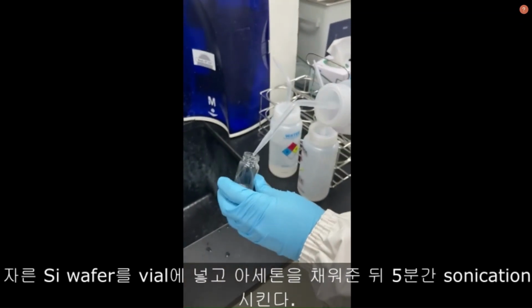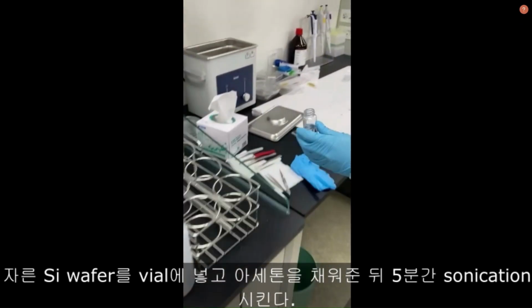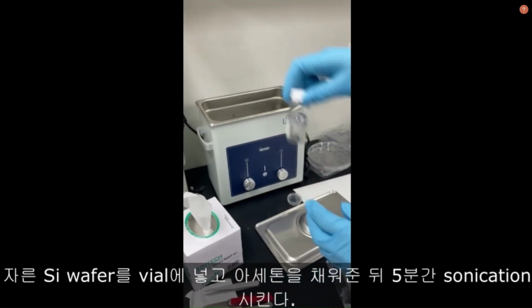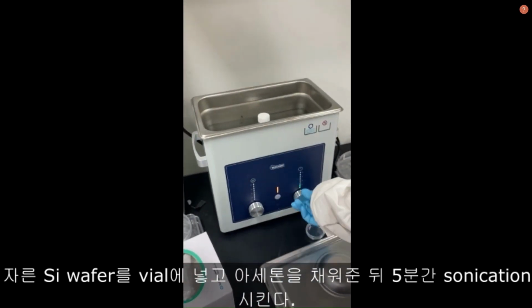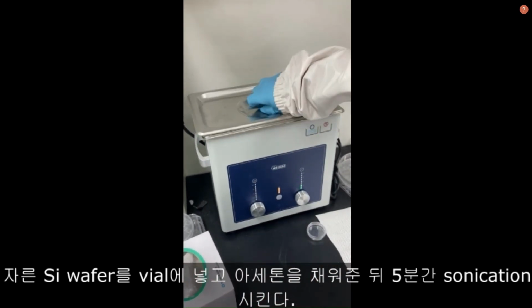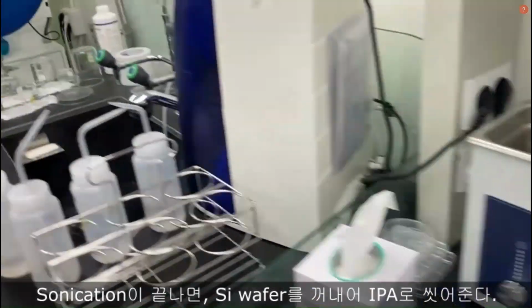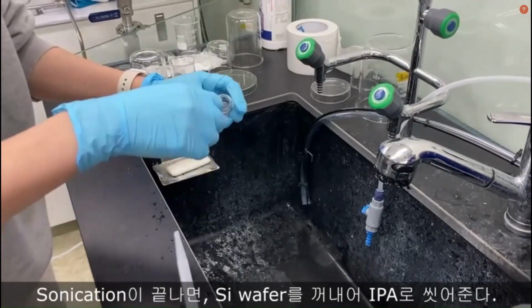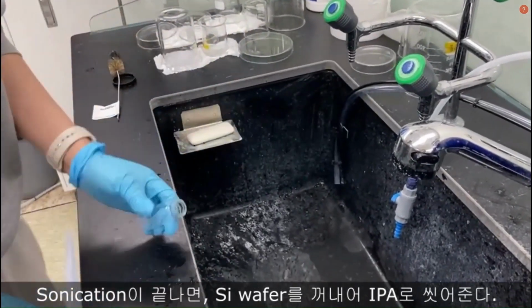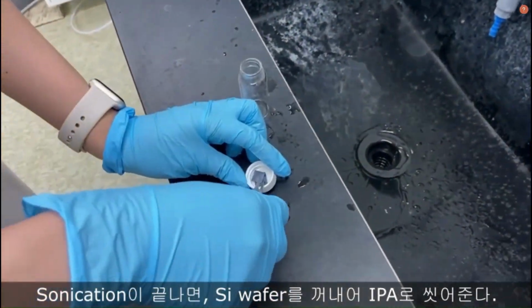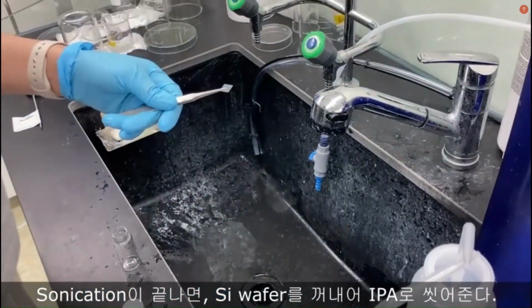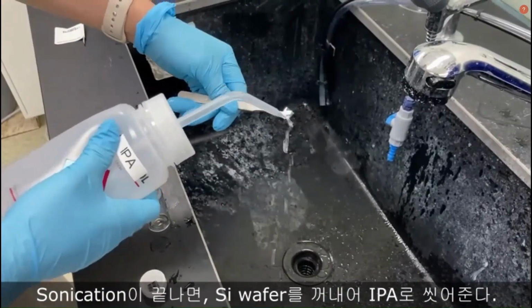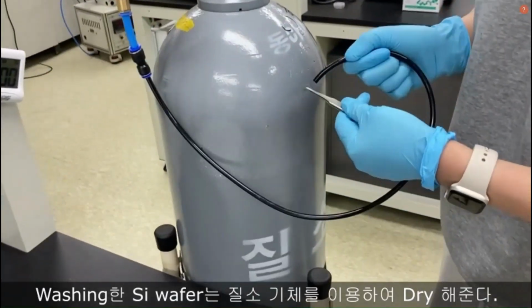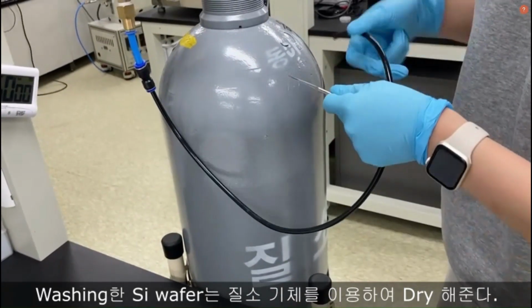Put silicon wafers into the vial and fill acetone, then sonicate it for 5 minutes. After the sonication is done, wash the wafers with IPA. Dry the washed wafers with pure nitrogen gas.